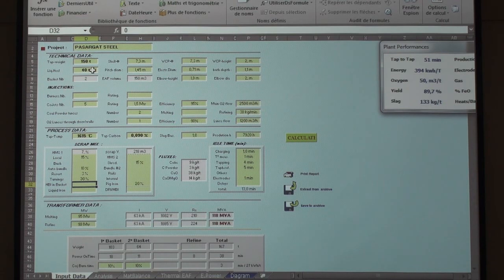If you extend the hot heel too much, of course you extend the surface, so you increase the radiation of the hot heel during tapping, and then you have to put more energy to reheat the hot heel. But as I heard, if we increase the molten state, we can use the electric energy, because a lot of the hot heel can help melting the scrap. Hot heel is necessary, definitely, but not too much.